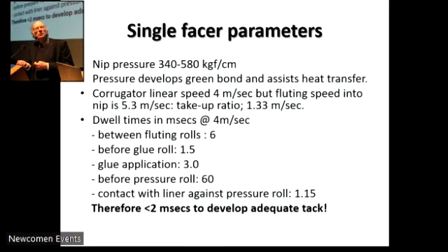The corrugator linear speed is 4 meters per second. But when you're forming the fluting from the fluting medium, you're actually pushing some of the paper out of the plane of the sheet. So effectively, in terms of its in-plane length, you're shortening the thing. If you take corrugated medium that has been made into a corrugated form and stretch it out, it comes out about a third longer than the corrugated product itself. And this is known as take-up.